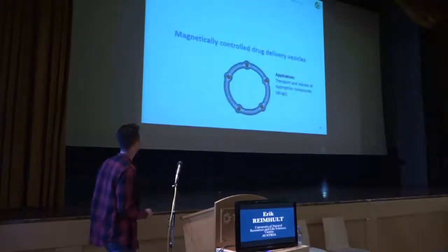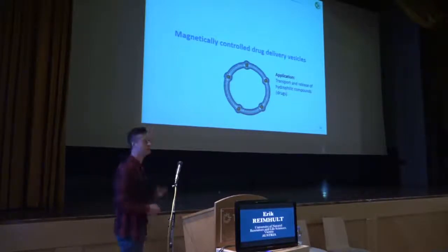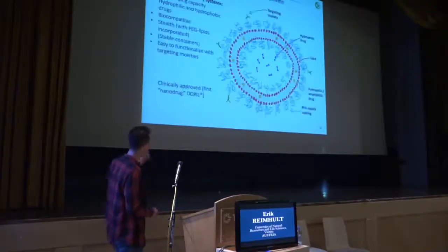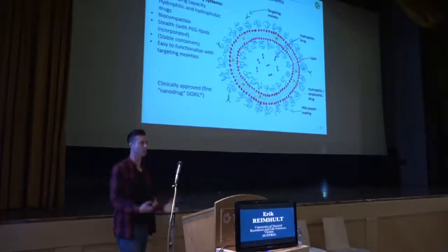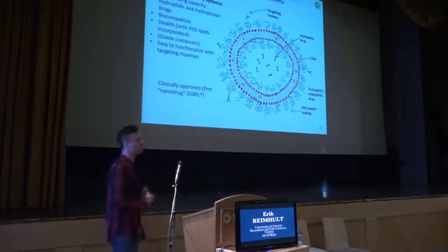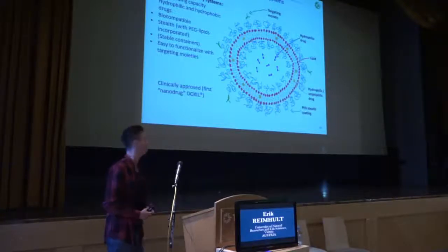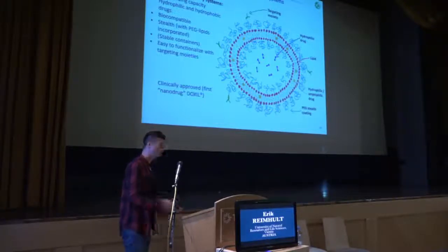So this example was not chosen randomly. The colloidal potentials that we engineered for these nanoparticles are about the same that you would expect to have from a virus particle or a 100 nanometer liposome, using simple Hamaker theory to recalculate the van der Waals interactions. So we think it also has biological relevance, not only relevance for people trying to do targeted nanoparticles.